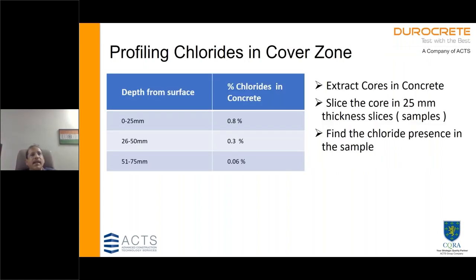Another common thing that is done for buildings that are already constructed is profiling chlorides in the cover zone. So if the depth from the surface is 0 to 25 mm, what you do is extract cores and slice those cores at 25 mm thickness, and check the percentage of chlorides in each of those slices. You will know the extent of ingress of chlorides inside the concrete, whether it has reached the cover zone, and then you can take protective measures.